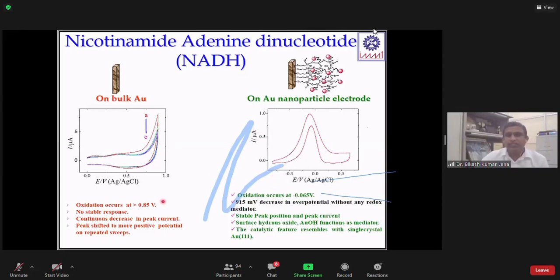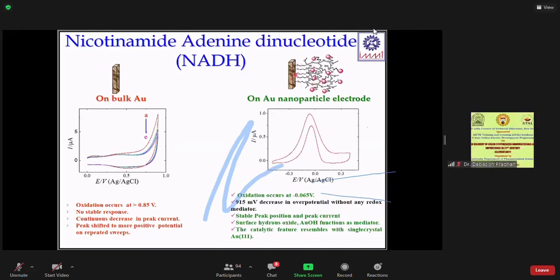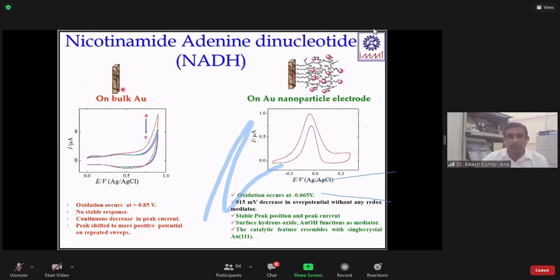So you can see, when we modified the electrode surface with the nanoparticle, we checked whether the response is good for NADH or not. You can see that without the nanoparticle-modified electrode, the NADH oxidation takes place at a high overpotential, around 0.8 to 0.9. But when you put the nanoparticle, it gets oxidized at a low potential, close to 0.1. Very low potential.